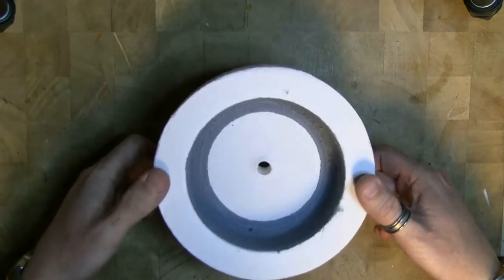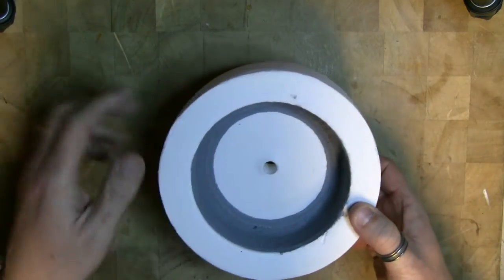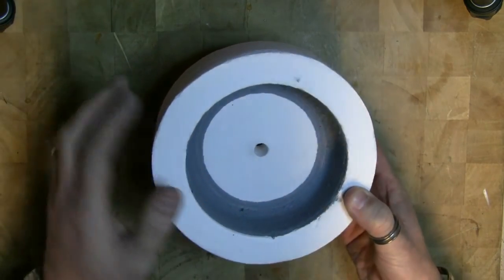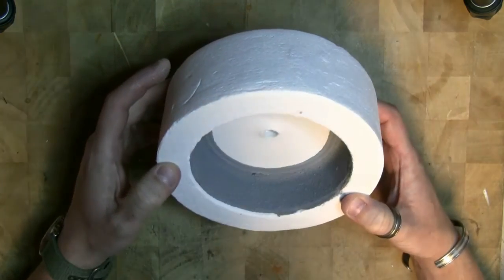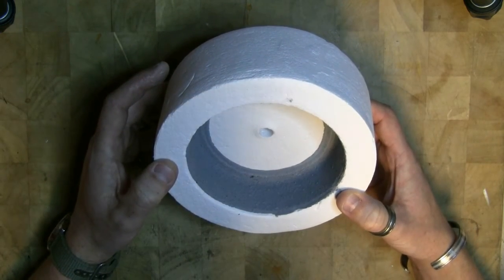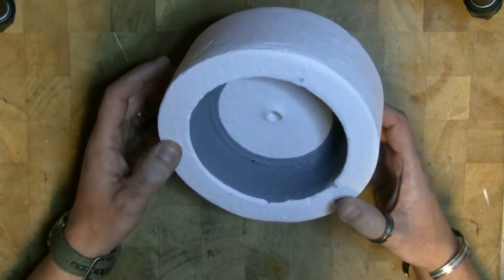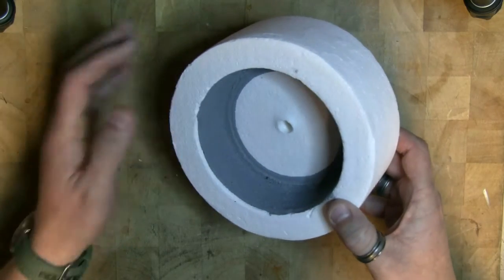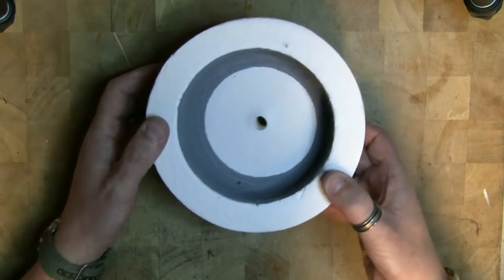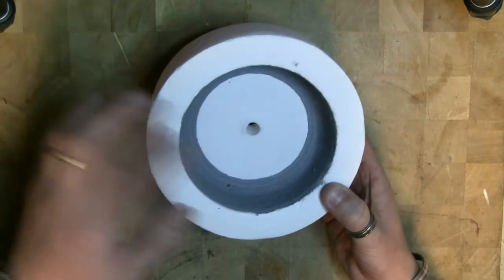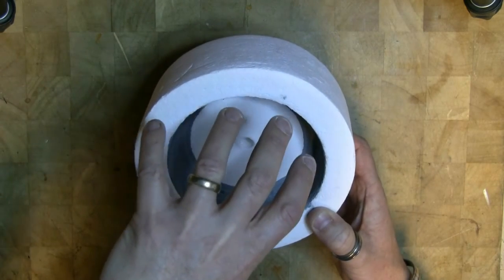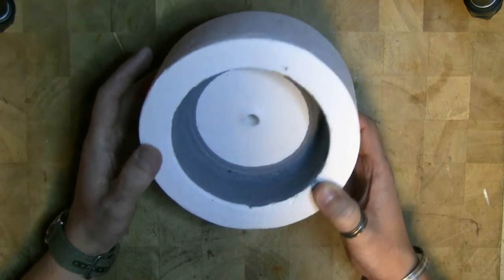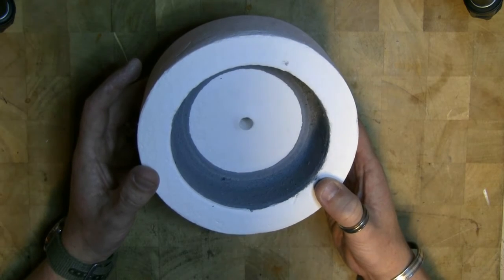Here's the clever bit. It's the same material hollowed out with the hole. This grey coating is called a susceptor, and they make it out of various materials. You can make it out of silicon carbide, magnetite, graphite, mixtures of the three. Some guys make it themselves, mixing it with sugar solution to stick to the walls, then baking it on. The idea is you've got a conductive ring, and the susceptor absorbs the microwaves, then gets very, very hot and directs the heat towards the glass, heating it very quickly, which is one of the problems with these kilns.